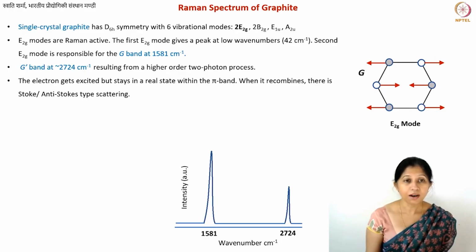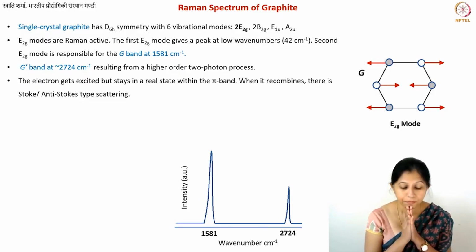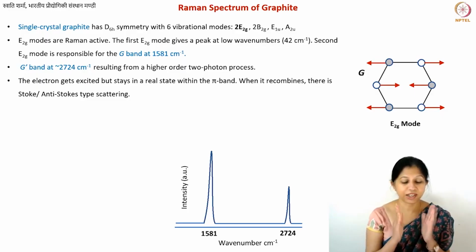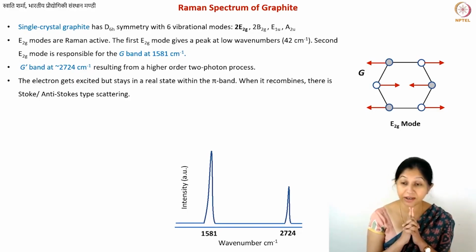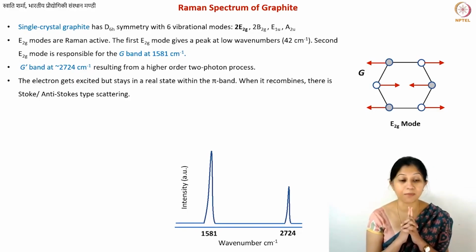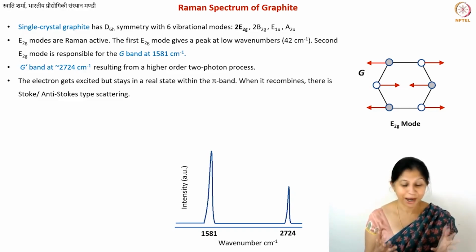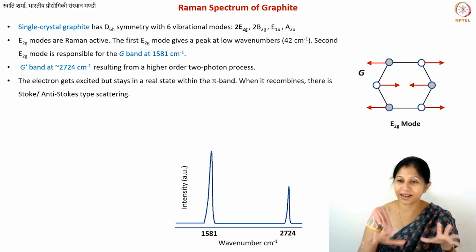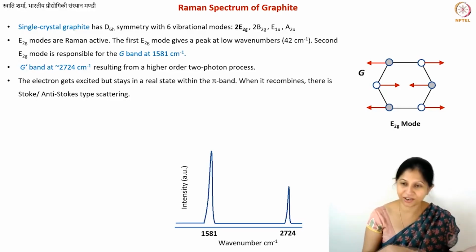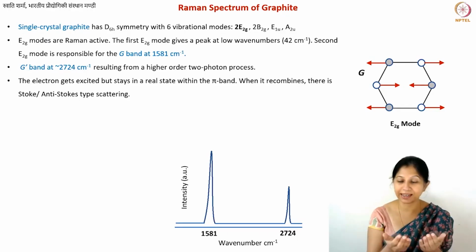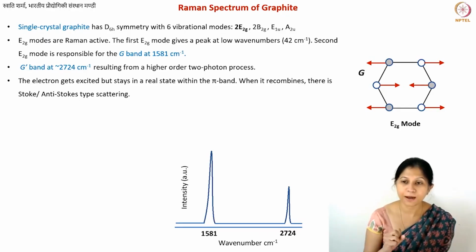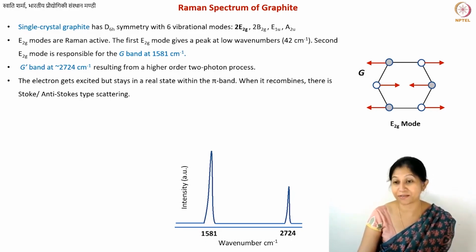Okay, fine. So basically, why we can get some very interesting results for graphene-like materials, and also pure graphene, is again because of the pi band. The unhybridized p orbital, the electron in that p orbital, is delocalized and forms an electron cloud. I told you that for most of the interesting properties of graphitic carbons, those pi electrons are actually responsible.